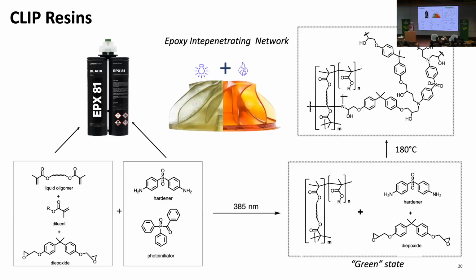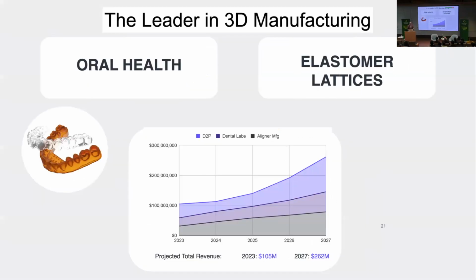And then we basically wash it or spin it clean, and then we do a step growth polymerization chemistry. And that chemistry can happen in an orthogonal fashion. It's basically a solid state polymerization in the form of a shoe or the pipe that I'm passing around. And that's how you get great material properties, using light just to set the shape, and then use polymer science to set the properties.